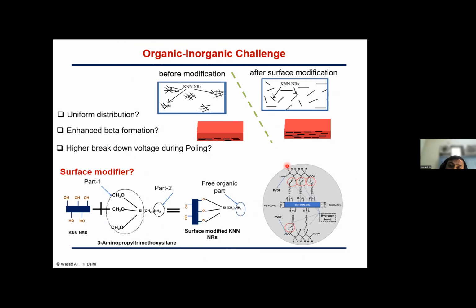And the major challenge is the inorganic-organic mixing, right? Inorganic-organic mixing is a major challenge. So what we have done, we have modified the piezoelectric filler with some coupling agent, which is basically organic in nature. So it will have more miscibility with the PVDF polymeric material, right? So agglomeration is less during spinning or film formation. And at the same time, dispersion is proper, better, along with the surface modifier, right? So that concept is also proven over here.